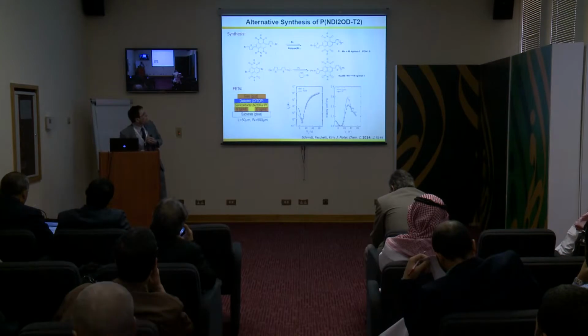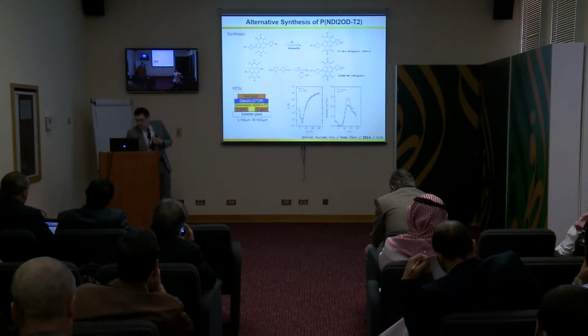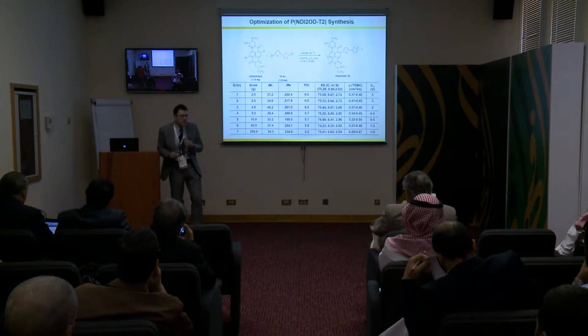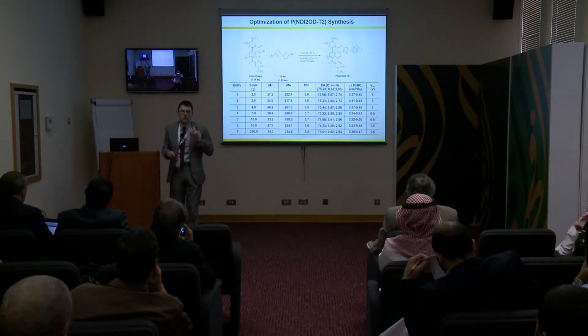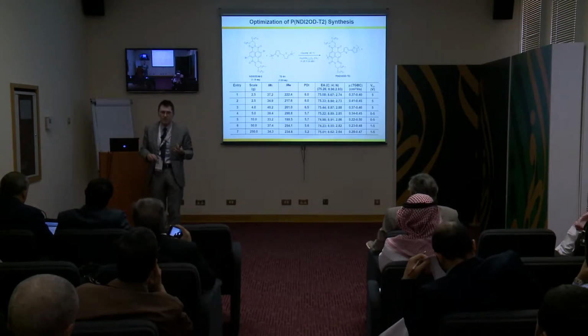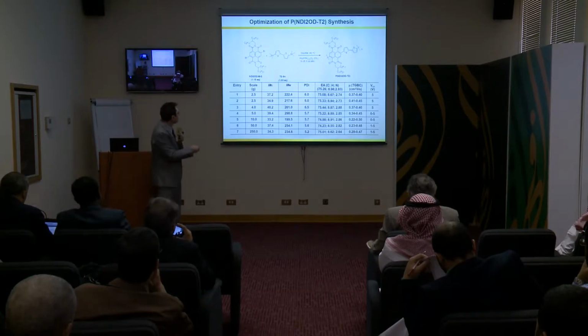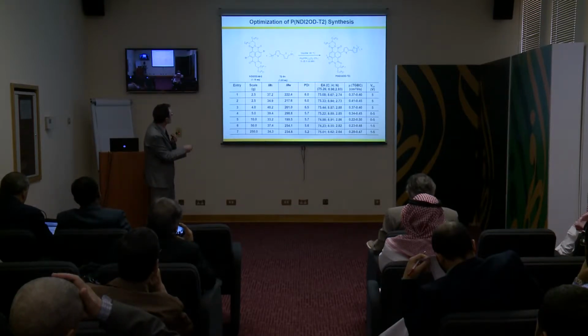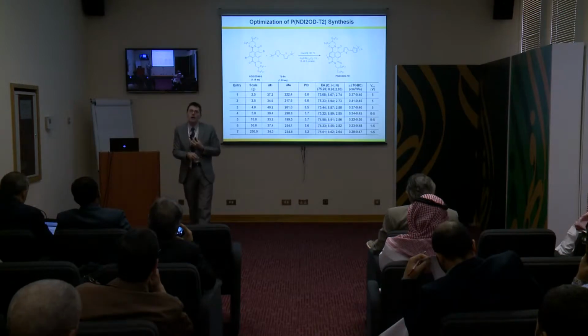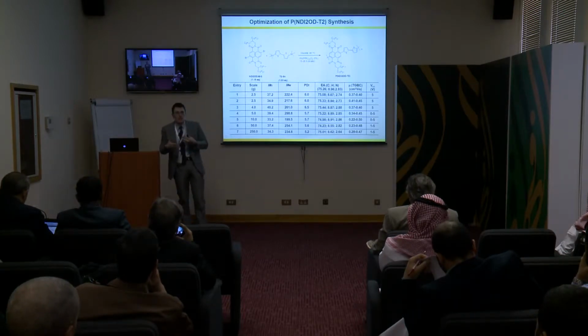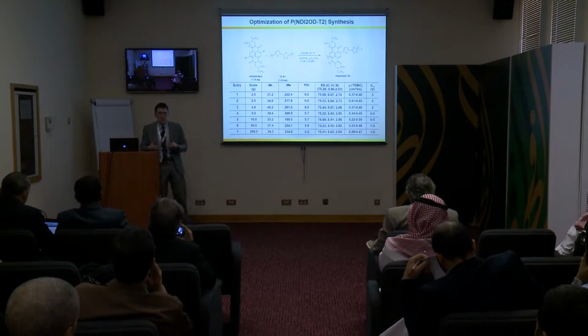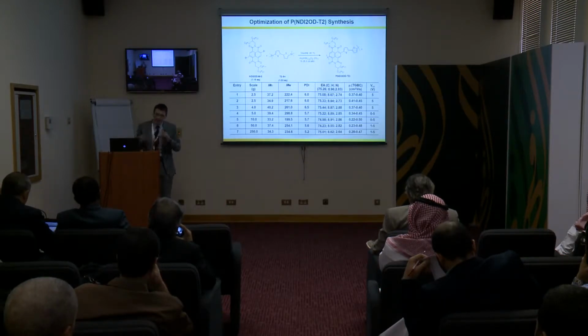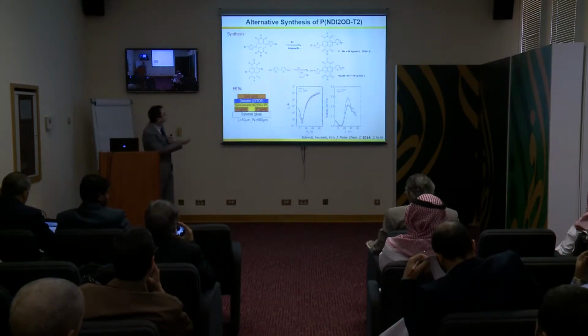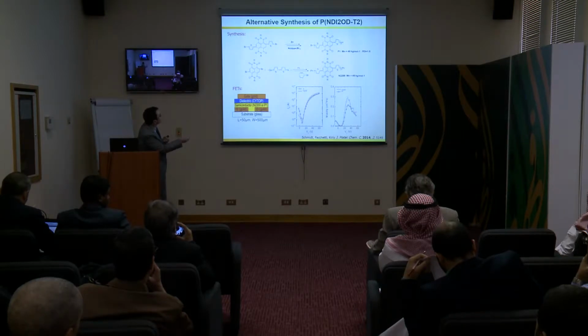What is the problem when you do this chemistry? The problem is, actually, I would say about 90% of the cost is to dispose the byproducts. And the most dangerous byproduct is trimethyltin bromide or trimethyltin hydroxide, which is produced in the chemistry and is present in a stoichiometric amount. So it's an environmental concern, but it's also actually a real issue. So we try to develop chemistries which do not need to have this